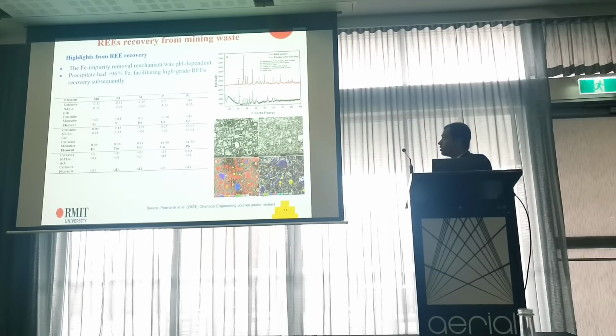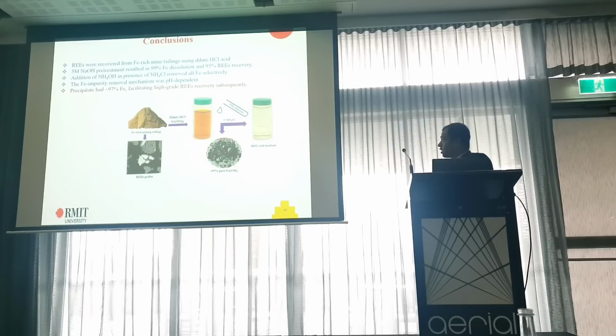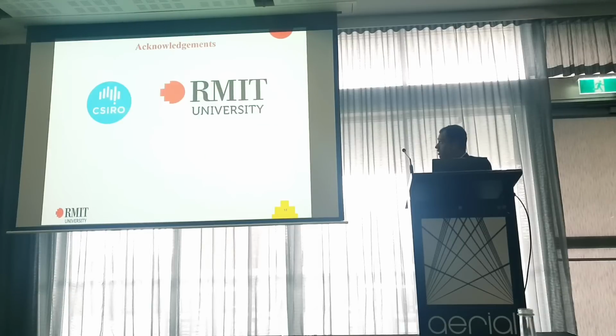the precipitate has around 96% iron, so we can say that a high rate of rare earth recovery was possible here. In conclusion, rare earth was recovered from the iron-rich mining sample, and the precipitate was around 97% iron, meaning the rest of the sample was rare earth. Our next target is how we can selectively recover each of the rare earth elements from the sample we are currently working on. These are the references, and thanks to CSIRO and RMIT for funding the project. Thank you very much.